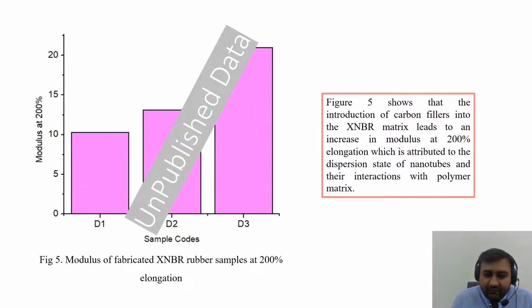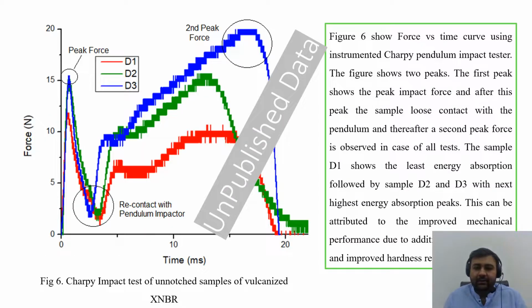This figure shows the modulus of fabricated XNBR rubber samples at 200% elongation. So this figure shows that the introduction of carbon fillers into the XNBR matrix leads to an increase in the modulus at 200% elongation, which is attributed to the dispersion state of nanotubes and their interaction with the polymer matrix.